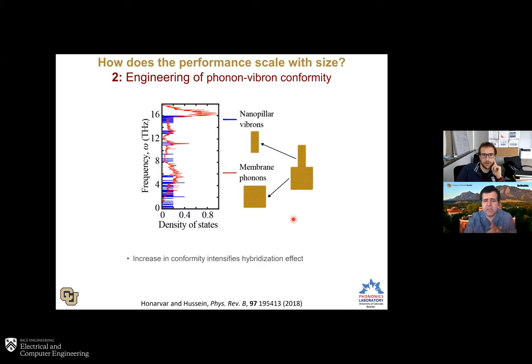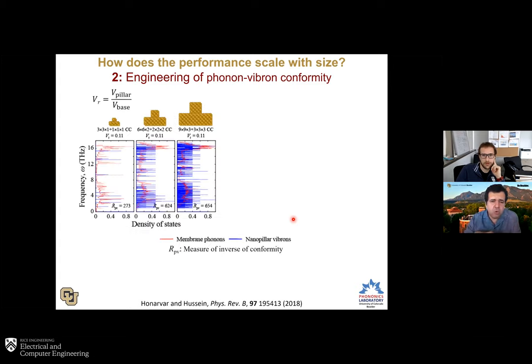I mean, they look very different. And in fact, that's not a good outcome, because the very effect that we're utilizing depends on the coupling being high. And for the coupling to be high, you would want these density of states to be matching, to be conforming. So we explored this aspect quite a bit.